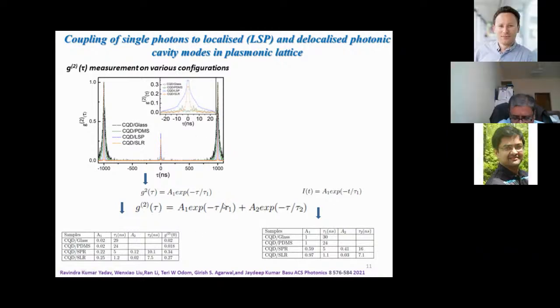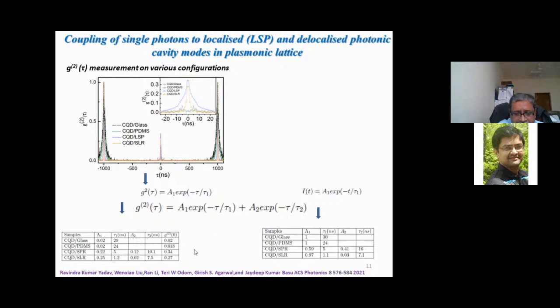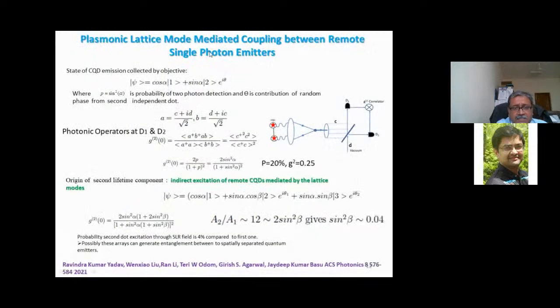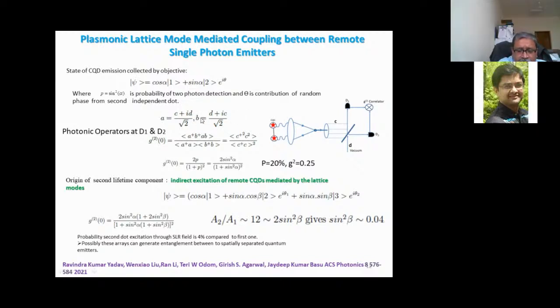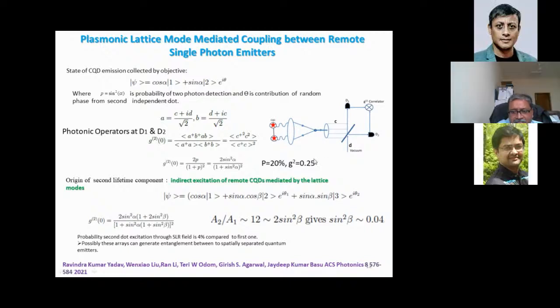The other thing is that, as we had seen with lifetime, we also see this type of behavior. You can fit this to time decay, and you can extract this, and we see similar behavior coming out here from the G2 curve. So to give a plausible explanation, this is a plausible way to look at two things. One, that there is an increase in this g2(0) value, and I'm not going into the details, but it can be explained in terms of the probability of two photons.